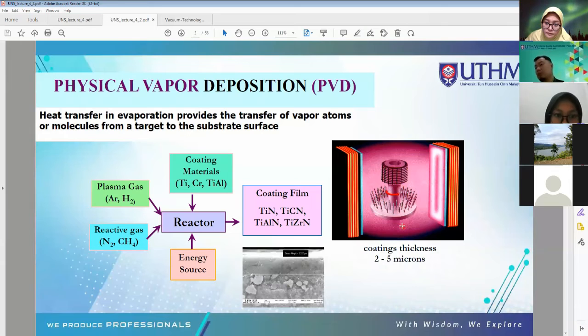On the right is where they want to coat a drill. If you see at the bottom here, this is the drilling head. We want to coat it with a hard coating. Most drilling heads are made of steel, and sometimes when you use the drill for quite a long time, it is not good anymore. So in order to make sure the lifetime of that drilling head is longer, we have to do a coating, which we call hard coating. Most of the time, hard coating uses materials like titanium nitride or titanium aluminum nitride, for example.